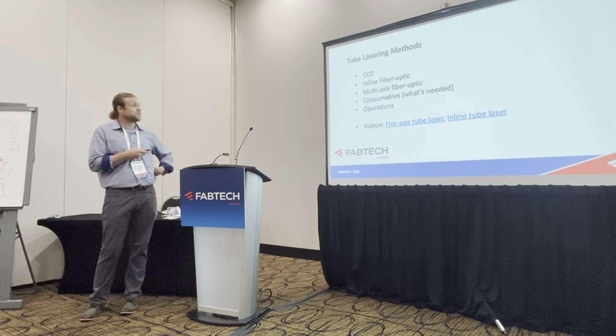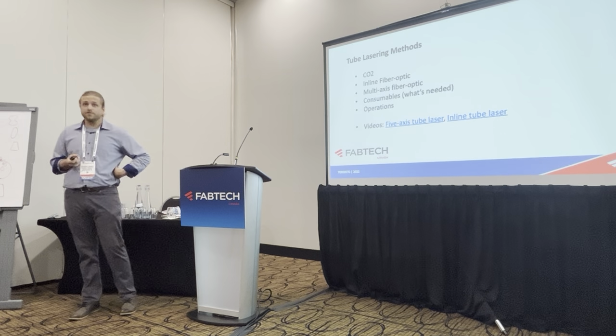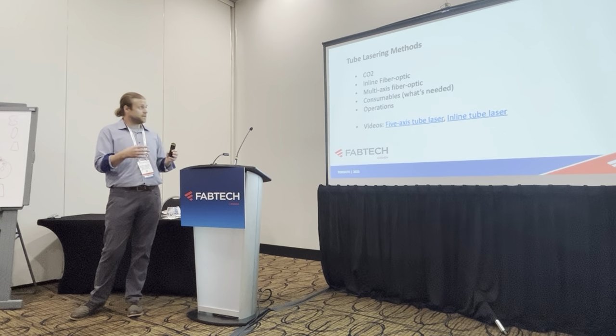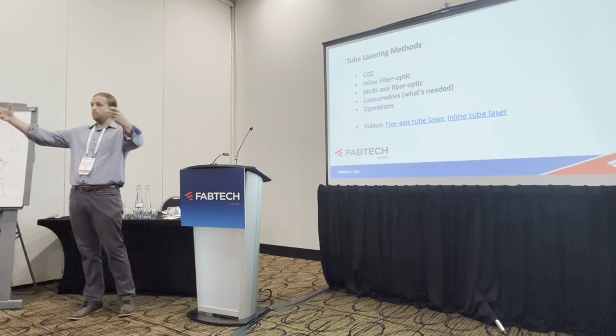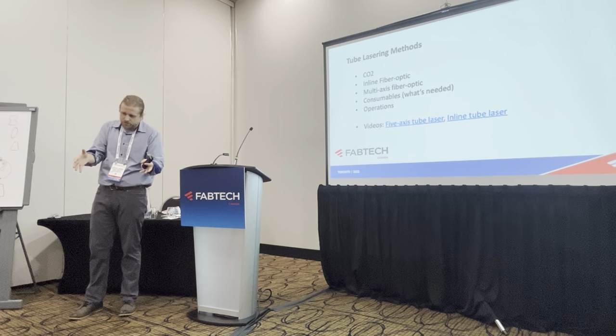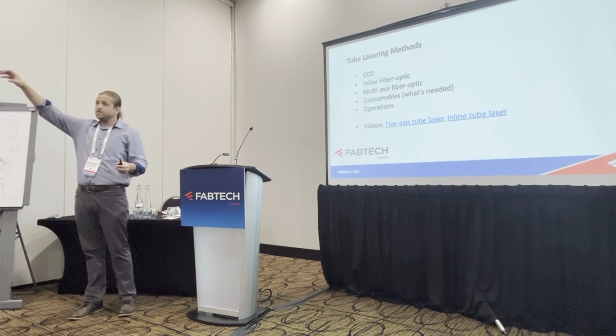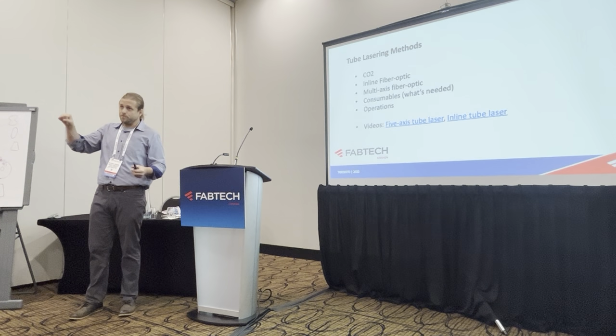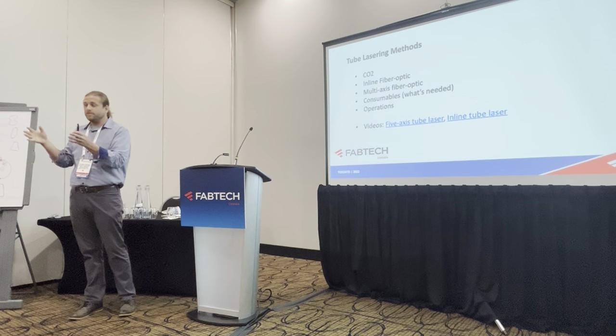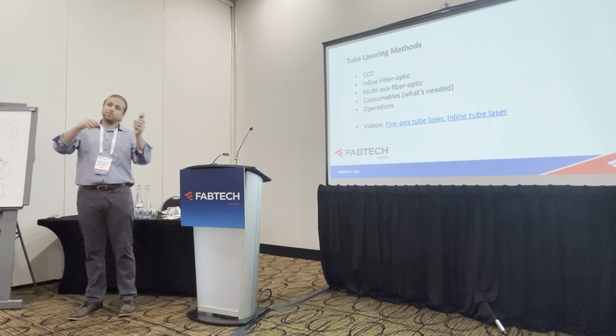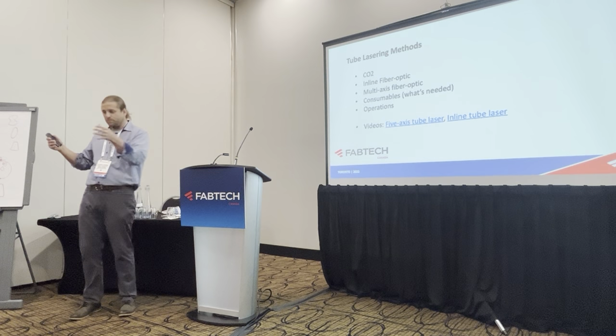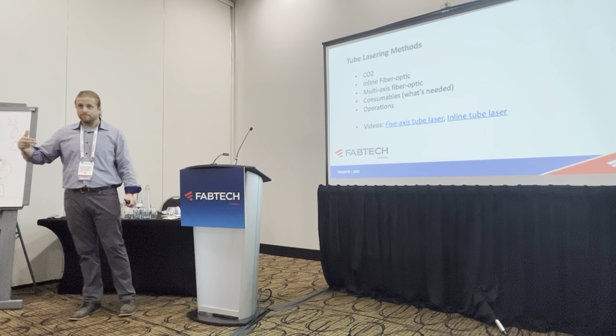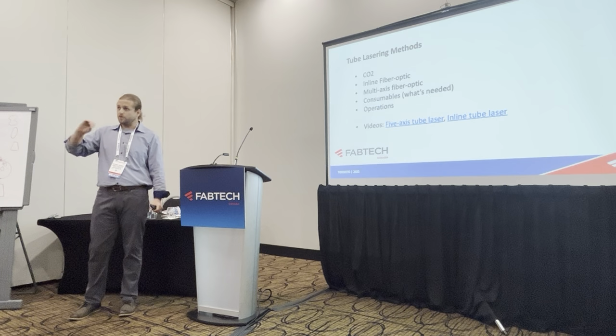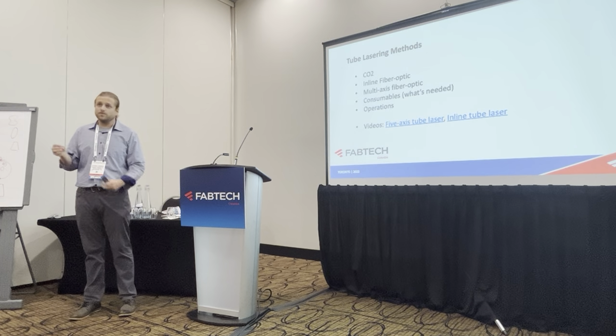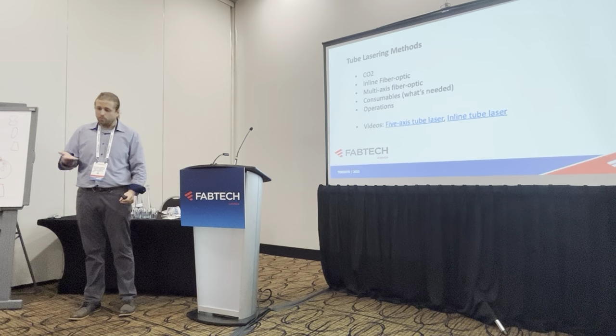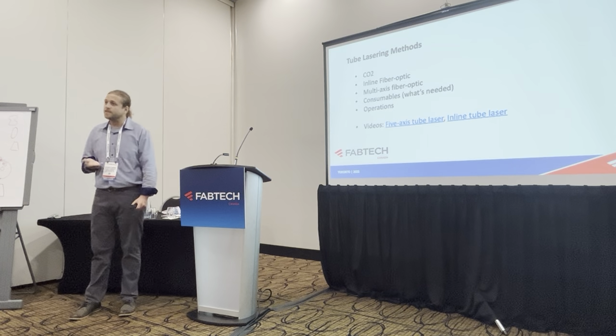You also have your multi-axis fiber optic lasers. Those are nice because, unlike a straight inline tube laser where it takes a raw 20 foot, you can hand load a straight up to 28 feet. The machine will automatically load the tube into the line. It will measure it. It will figure out what the length is, and then it'll put it into the process line. It'll go through. It can actually check weld seam. It'll place the weld seam in location to where your holes are for bending. It has cameras and it'll help to center holes as you're cutting them too.